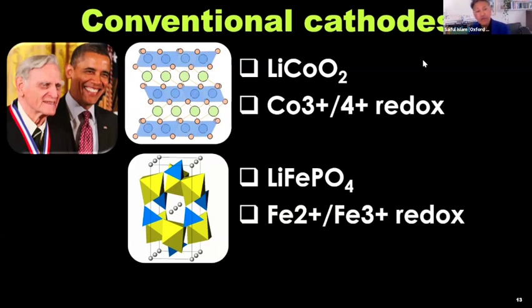The other material, which is becoming increasingly important, is lithium iron phosphate, which relies on an iron 2+, iron 3+ redox. The structure is quite different from a layered oxide, and you can see it's made up of yellow iron octahedra and the blue phosphate groups. And I'm showing you the lithium ions in grey.